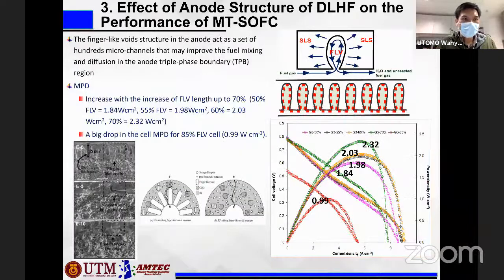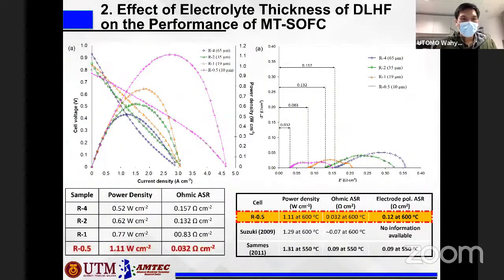Between all of these parameters, for example substrate resistance, of course we have the resistance from the substrate itself, the resistance within our catalyst itself, and maybe with the electrolyte. What's the main factor that we need to be concerned about when we do measurements?